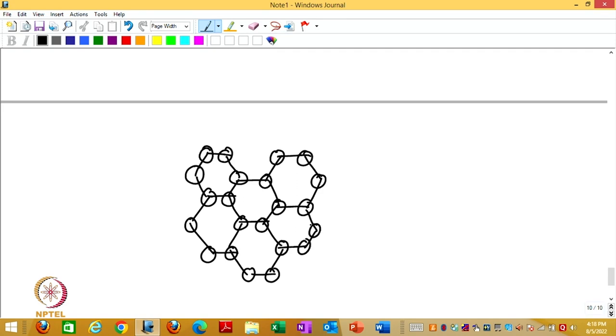Here if I want to figure out the translationally equivalent points, then if I select the center of this atom, I know that the nearby one was not translationally equivalent. So, I cannot select that. So, I will go and select the alternate ones. So, the centers of all atoms are not forming a lattice. Only the centers of alternate atoms are forming a lattice in graphene.